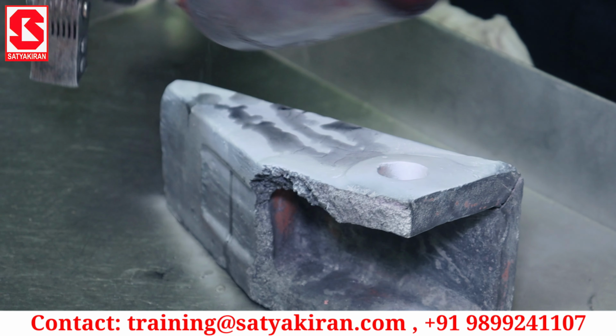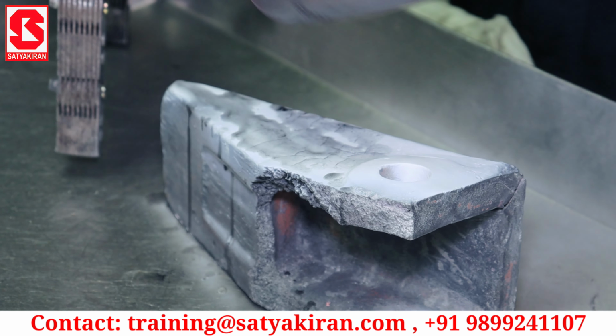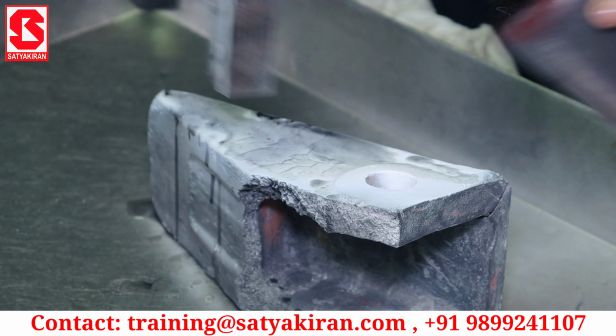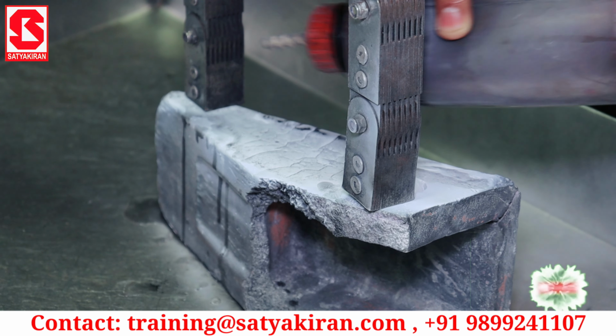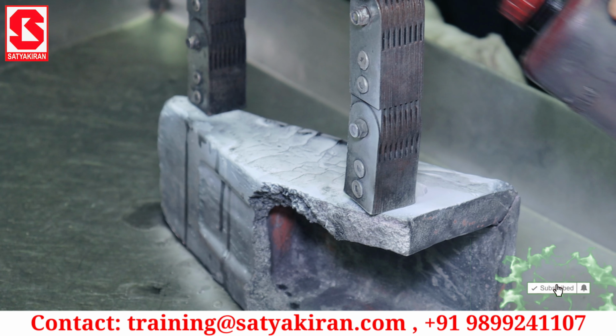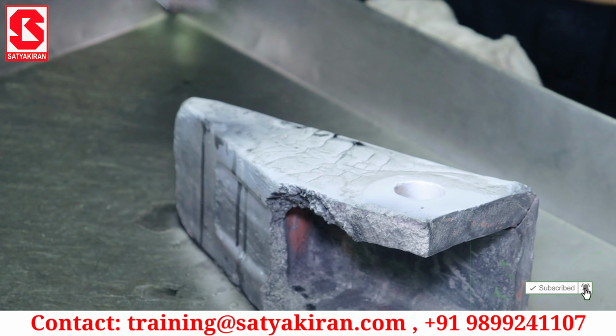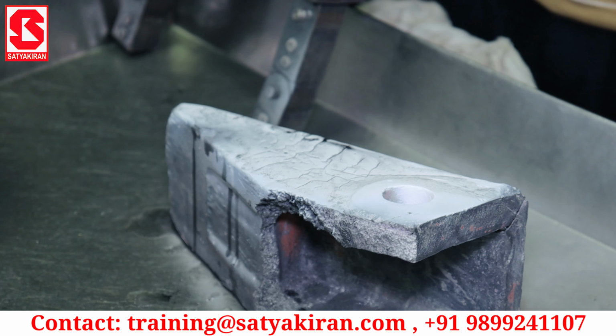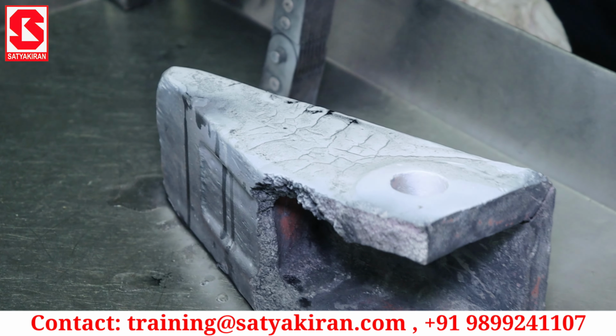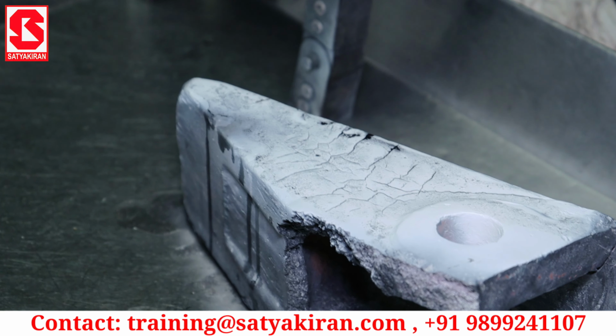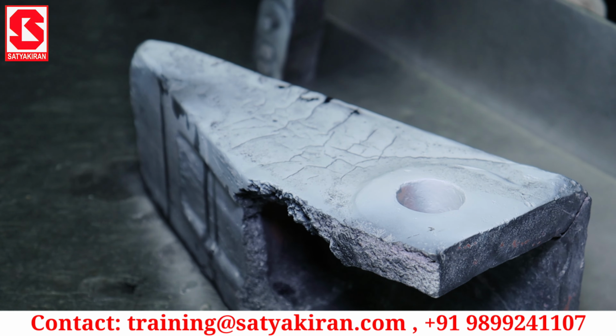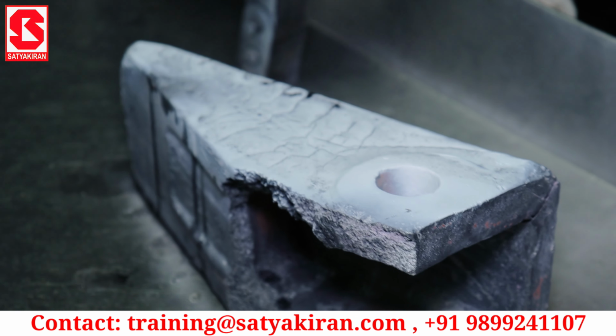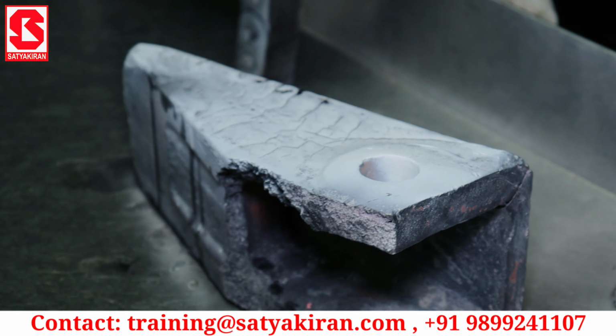White particles, black particles over white, and voila. You are still able to see the cracks even without magnetization. And when I started magnetization, I'm able to see more. So this was an example of residual magnetization, where even without magnetization, I was able to detect the cracks.